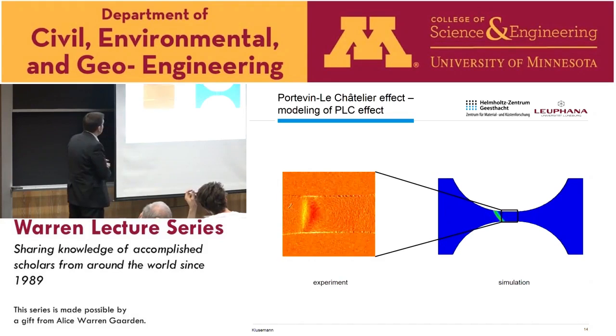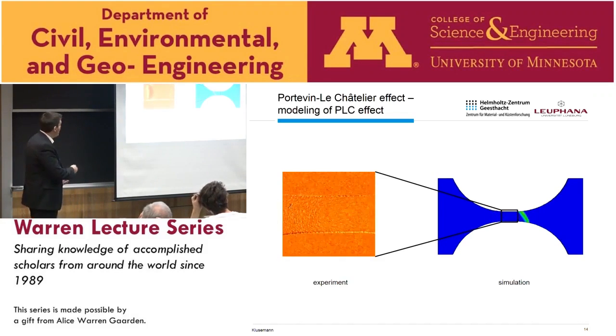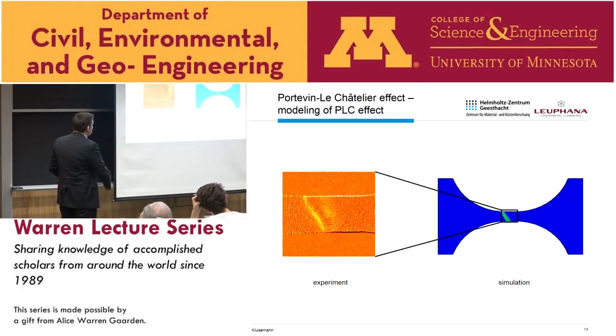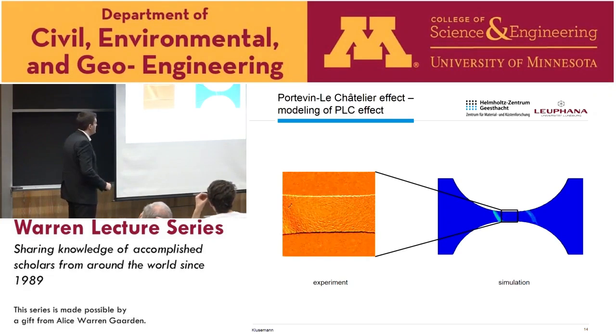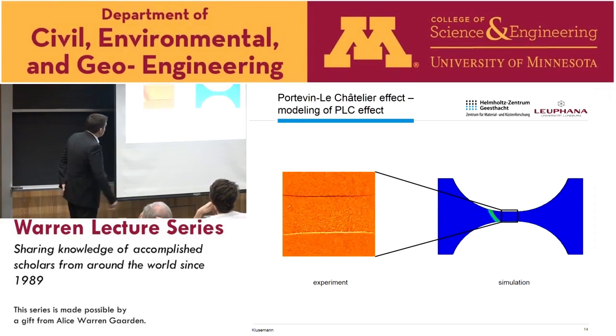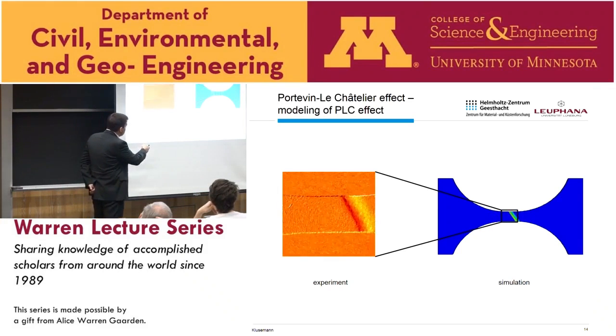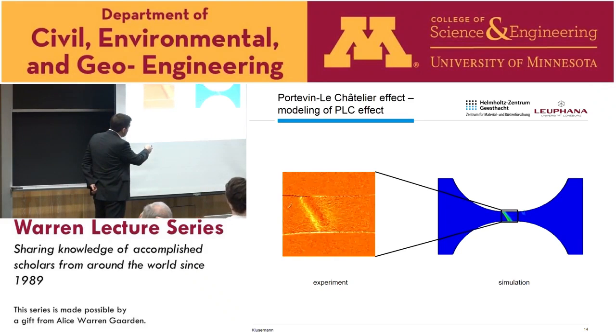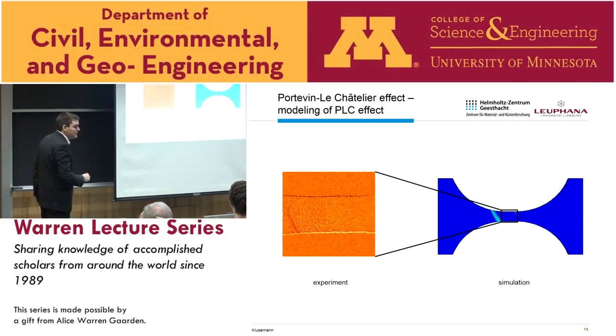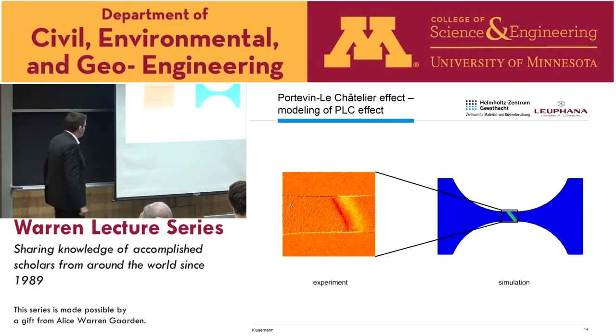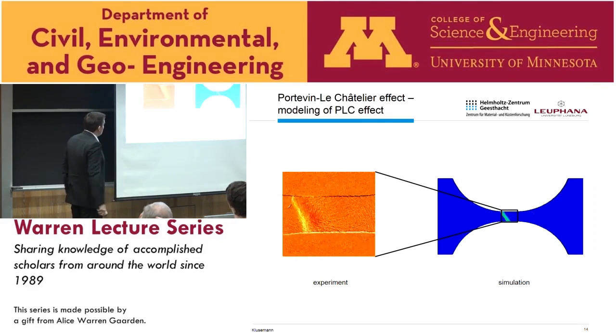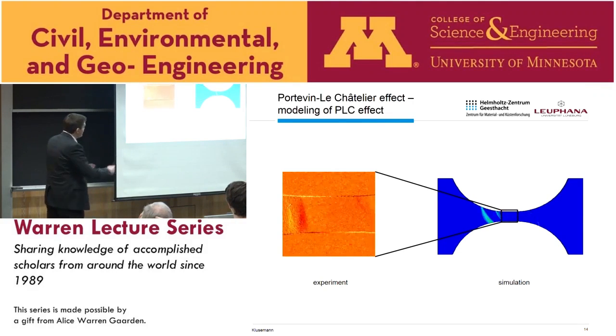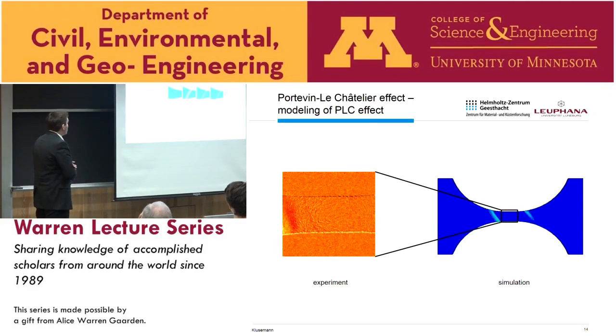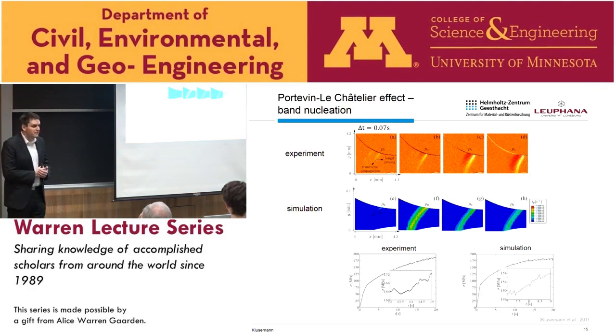So here you simply can see a comparison now. On the left you see the results of our thermocamera, where the experiments were done in Dortmund. And on the right you see the simulation for one specific strain rate. And what you can nicely see is, of course, we sometimes have a PLC band which runs through it, but sometimes it also disappears. So here we have a continuous band now. We see something similar like this. So this was a strain rate which was intermediate between A and B. This was a kind of mixture, just to show how we obtained some results experimentally as well as numerically.